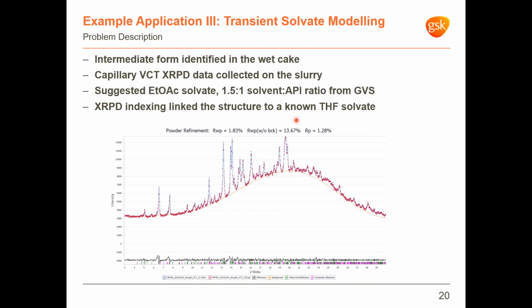And I should mention that in the methyl THF solvate crystal structure, from analysis of the Fourier difference map, a 1-to-1 API solvent stoichiometry could be estimated, but the methyl THF solvent was eventually removed by means of the SQUEEZE routine in PLATON due to disorder.